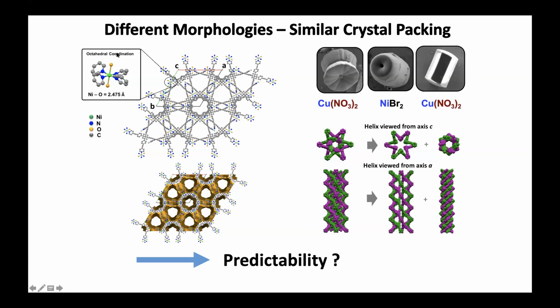We believe that the origin of the chirality in the crystals is the coordination chemistry of the ligands to the metal center. The green dot here is nickel, and you have here 4 pyridine units from 4 different ligands coordinating to the metal center in a kind of propeller type arrangement. So you have a kind of chiral arrangement around the metal centers, and each metal center has the same chirality in one crystal.